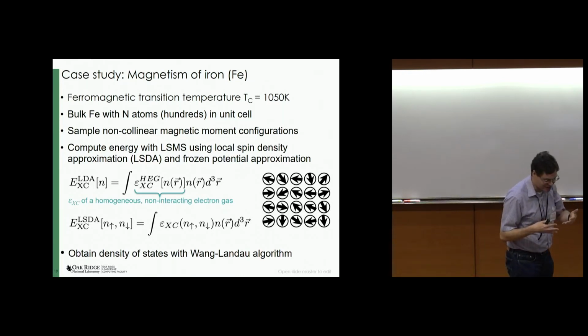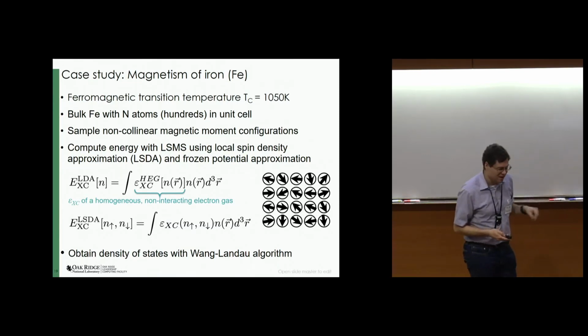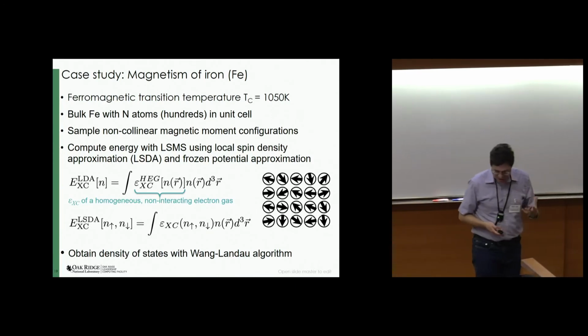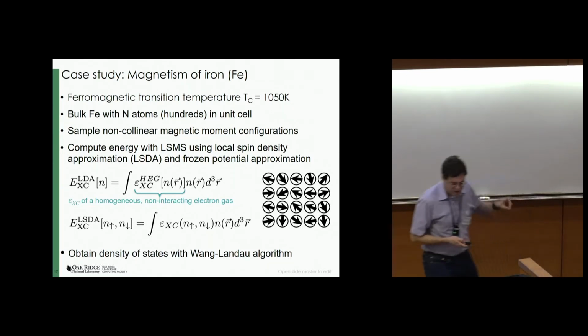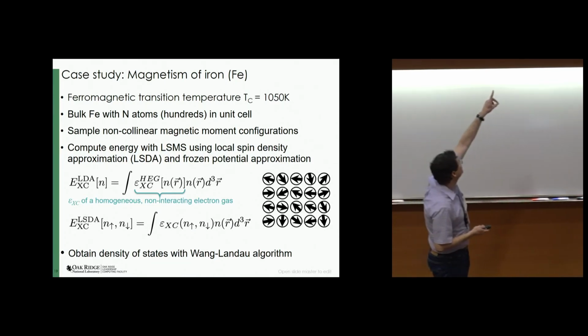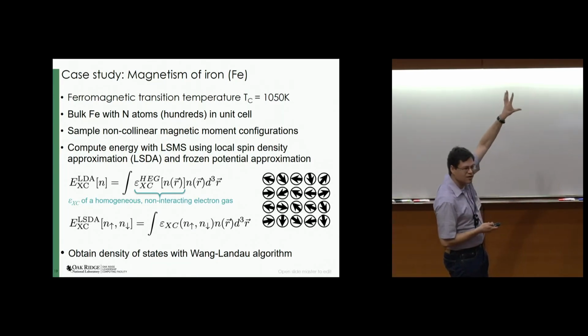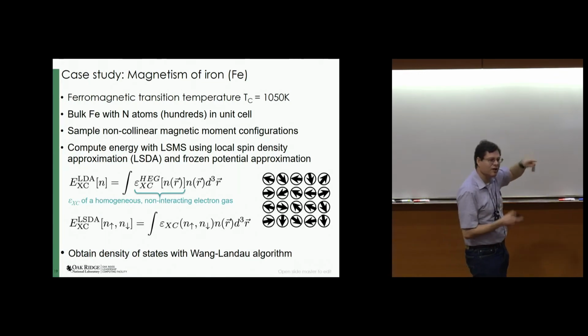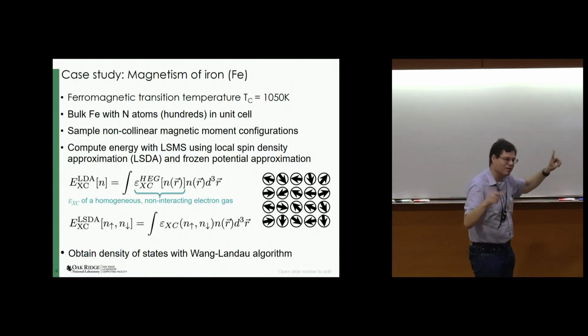When physicists talk about this, there's the electronic one, which we don't really care about, except that it's required in solving the Schrödinger equation, with a constraint that ensures that the moments point in this randomly chosen direction. If you just solve DFT without this constraint, you will always find the zero temperature ground state.